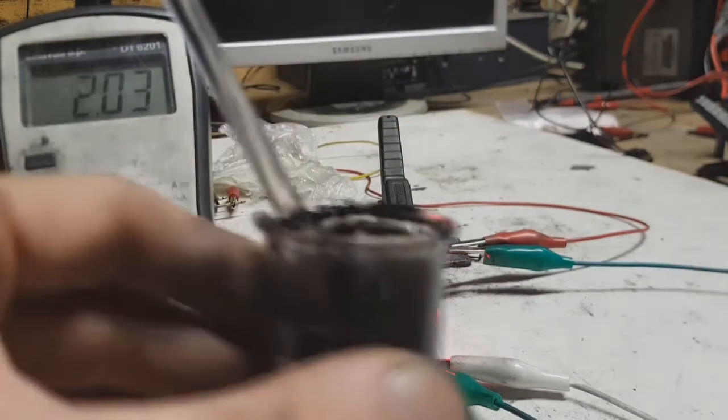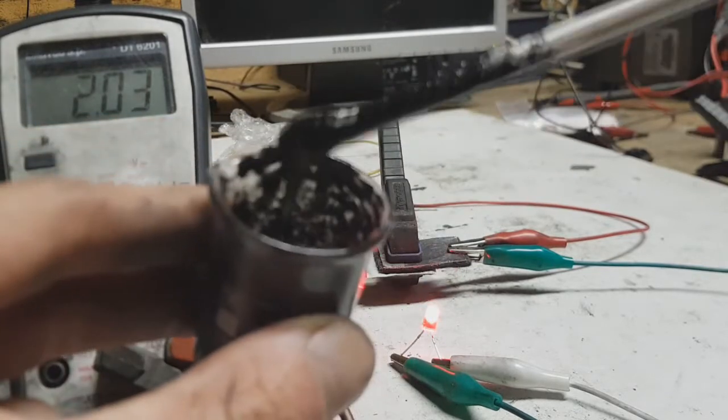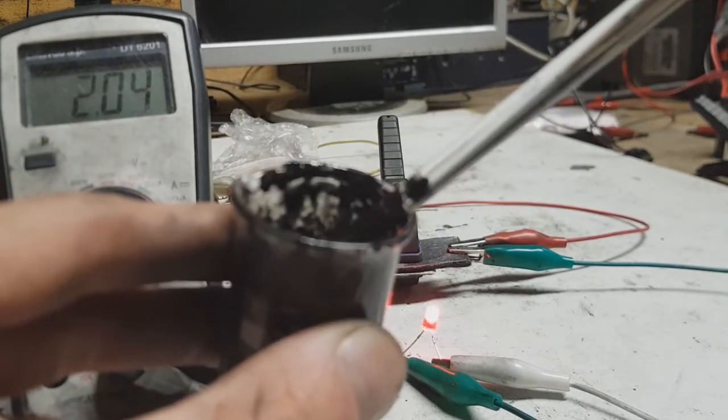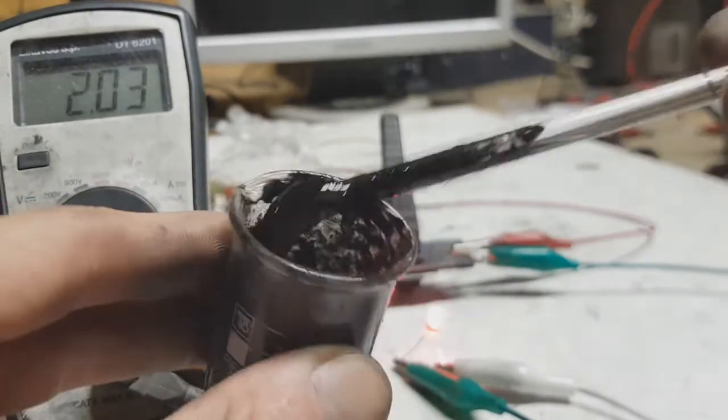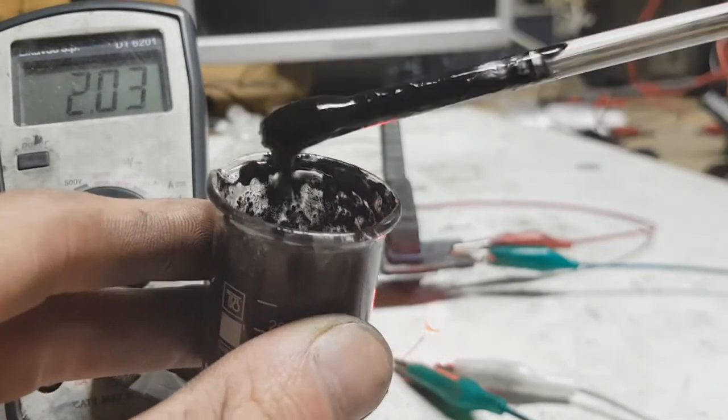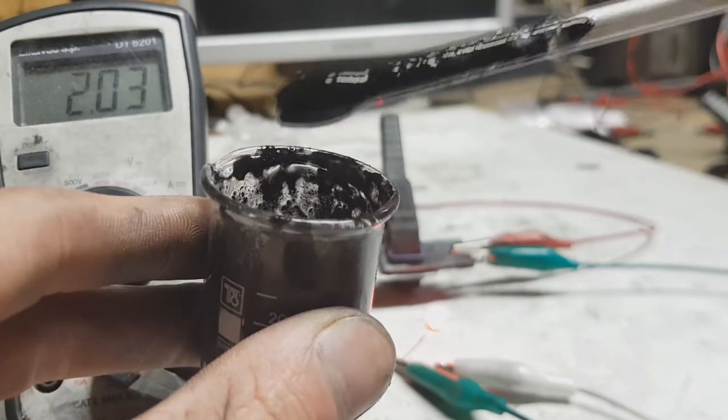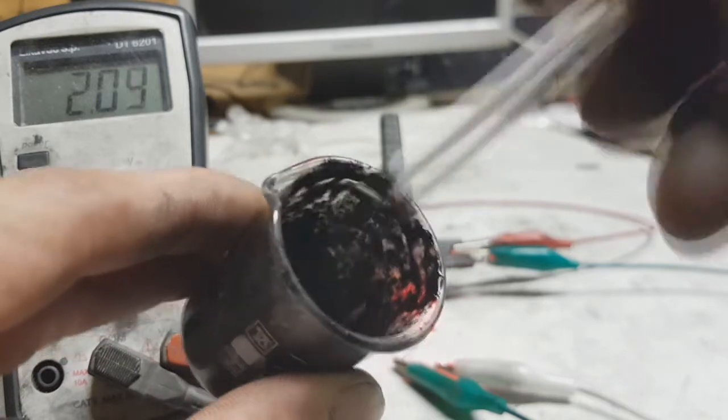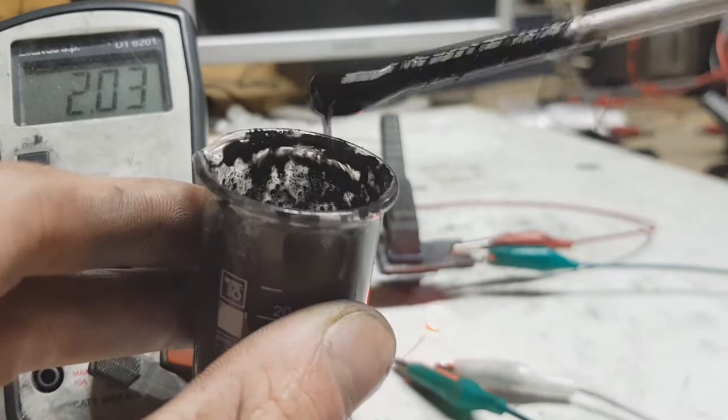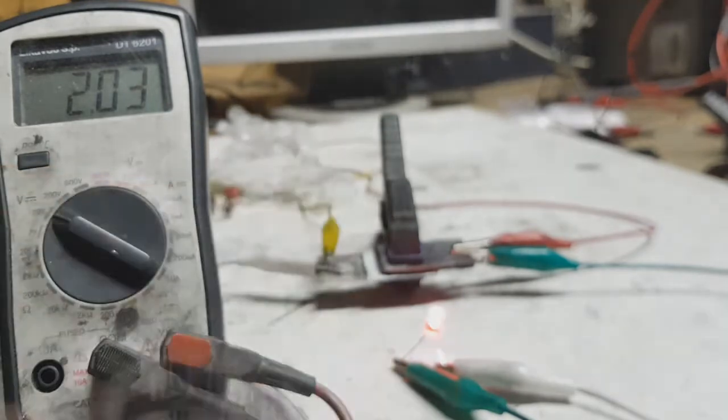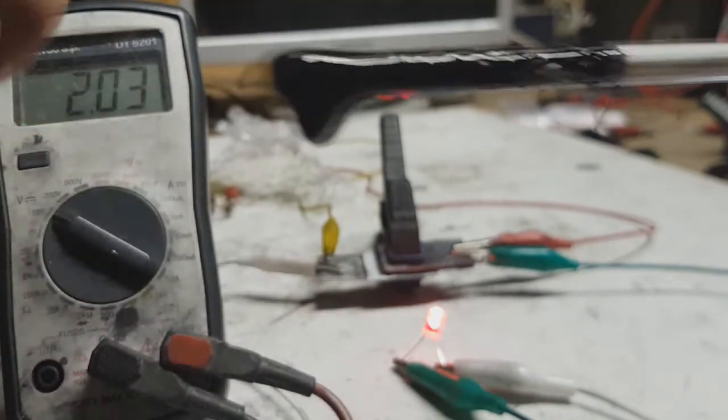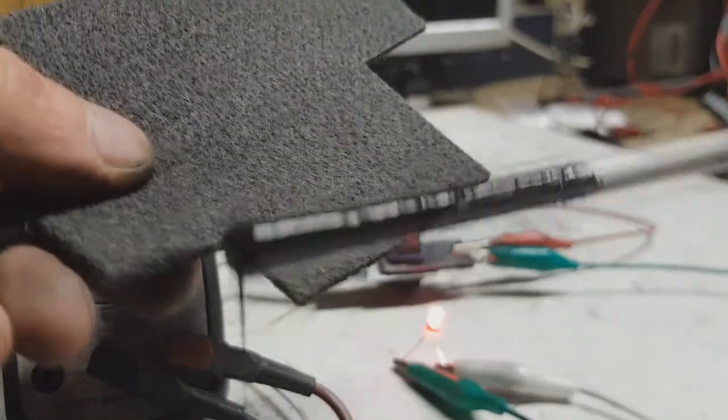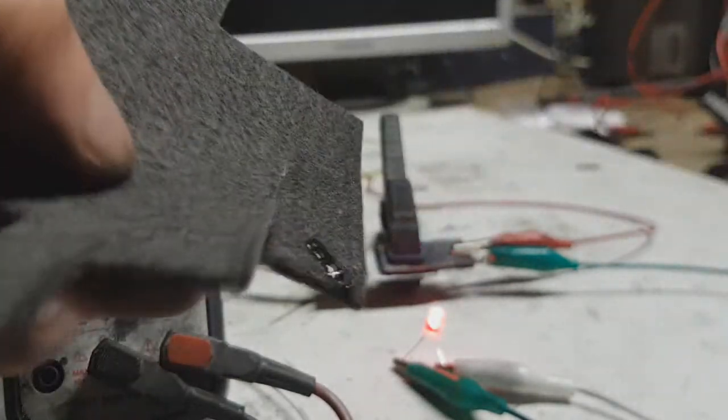When you make this electrolyte, this electrolyte also has some active material for the positive side. So you can put manganese dioxide and some carbon black and mix all this together. Then you need to only put this electrolyte on this carbon fiber.